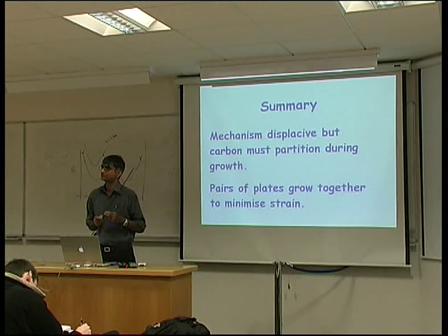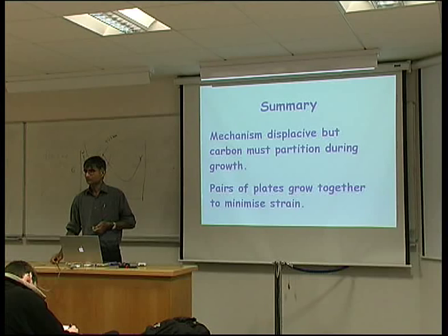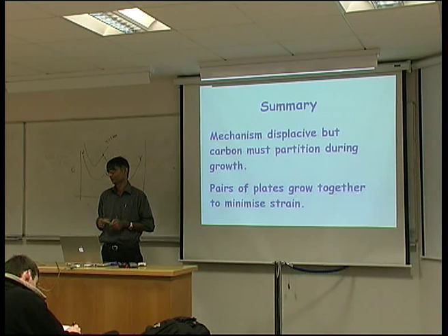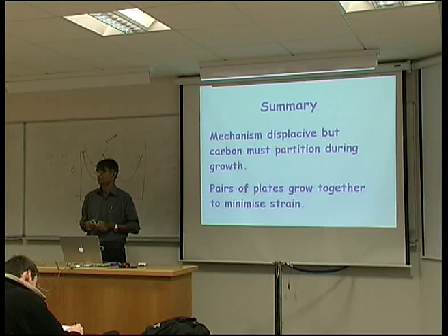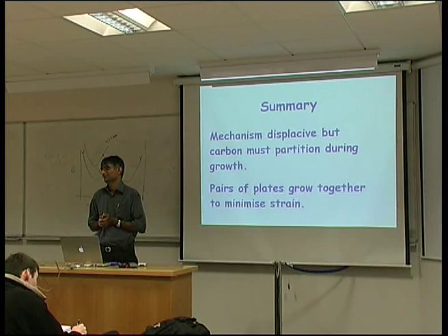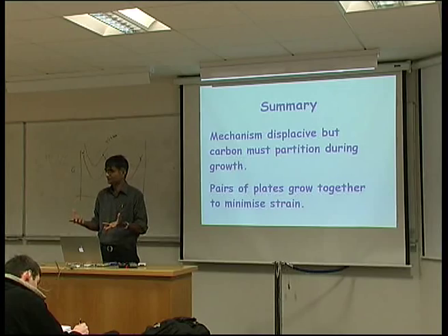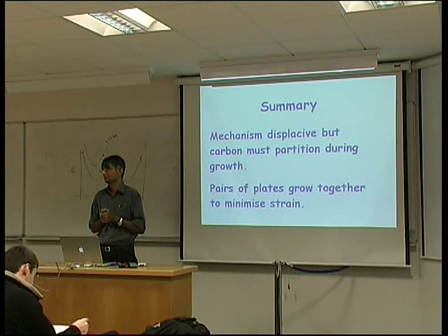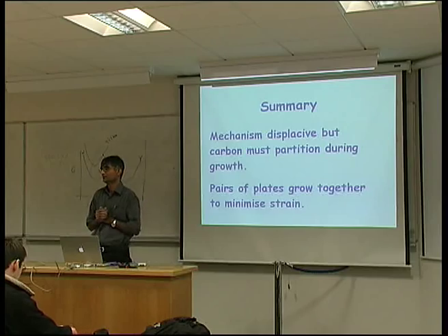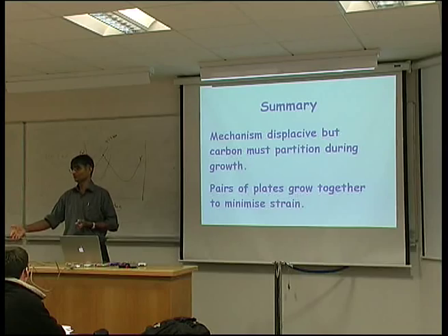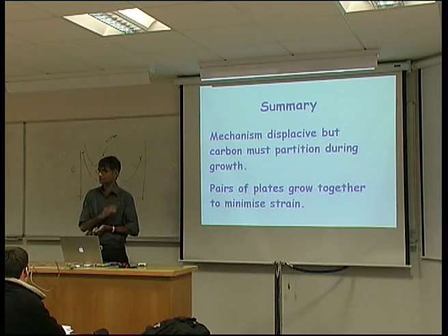So you still have shape memory, or did you reverse it? It is difficult to reverse it because you've done something irreversible, which is the partitioning of carbon. The carbon can just diffuse back in. Yeah, but how do you cause that to diffuse back in using a stress? The diffusion is uncoordinated, it's irreversible. So you cannot reverse that part. There's no chance of reversing this by applying a stress. You know, to reverse something, you cannot have dissipated energy. And diffusion actually occurs in order to dissipate energy. So there's no chance of a shape memory.